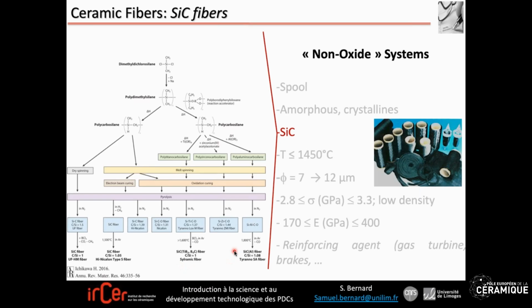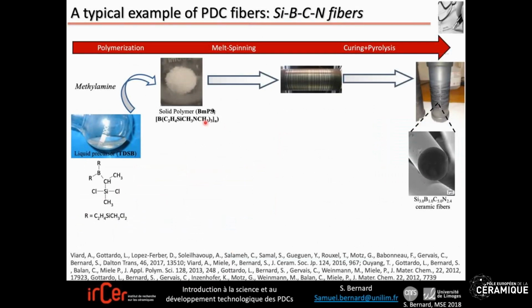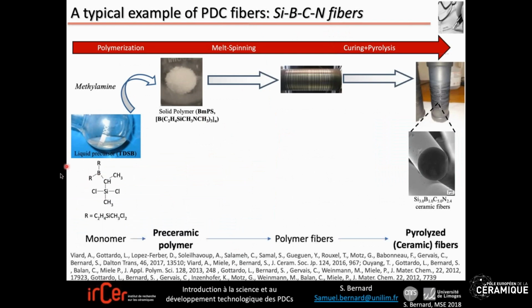So the PDCs process to fabricate these fibers is the same, whatever the fiber composition. Let's consider the example of SiBCN fibers we produce in our institute. You can recognize here the different steps of the PDCs process: the monomer, chemical modification with a low molecular weight compound, methylamine, to produce a new precursor, the pre-ceramic polymer. Then shaping, we use spinning in the molten state. This is the best method to produce fibers through the PDCs process.